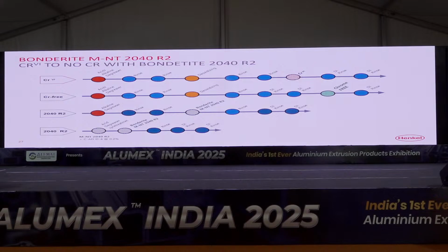But if we change to 2040, we have another concept. It's a concept that we can use as a conversion metal pretreatment product, but it can also work as a cleaner coater. What does a cleaner coater mean? It means that we can etch and we can treat at the same time. So we are etching the material and we are creating a self-controlled conversion coating. So it means that we can establish two stages with the same product, skipping the rinse in between because we are talking about the same product.